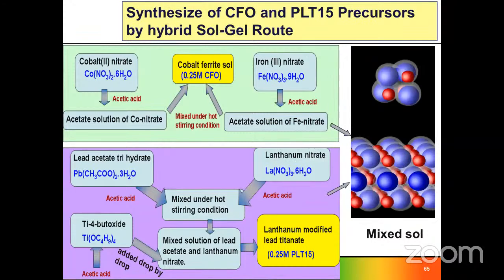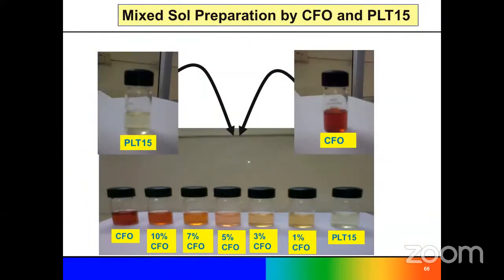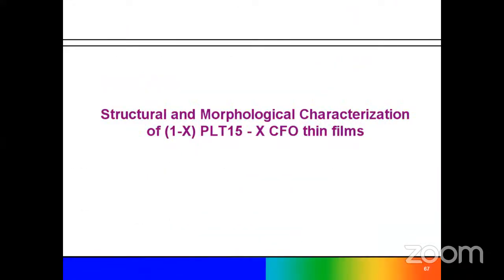Here we use the sol-gel synthesis process for making the magnetic material and also the piezoelectric material, using lead acetate trihydrate, and finally lanthanum modified lead titanate and cobalt iron oxide. Then finally we mixed these two in different compositions of cobalt iron oxide in a matrix of PLT15, and optimized the doping percentage where we get the maximum magnetostriction coefficient.